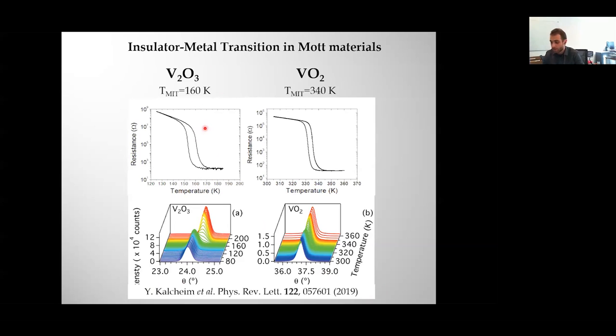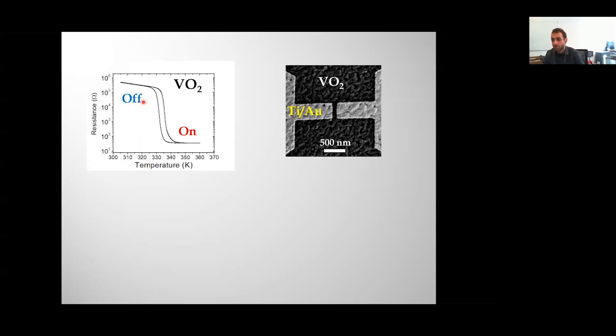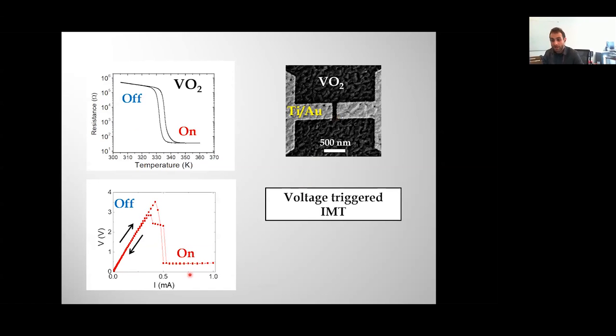So now you take one of these materials, like VO2 that we have here, and you pattern two electrodes, so you can pattern them very close together, so you can apply a very large electric field just with a few volts. So then you apply some current or some voltage, and you can do a voltage triggered insulator to metal transition, which is what you see here. The material is insulating here, and then you use it to go into the metallic state.